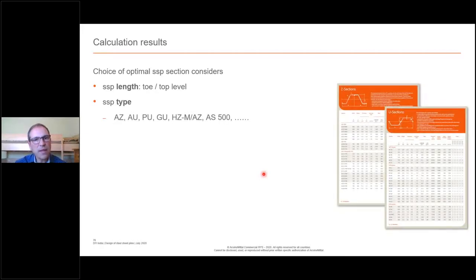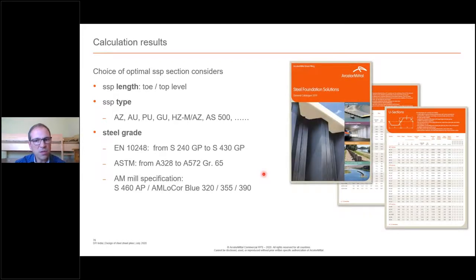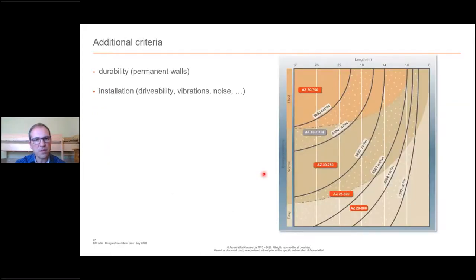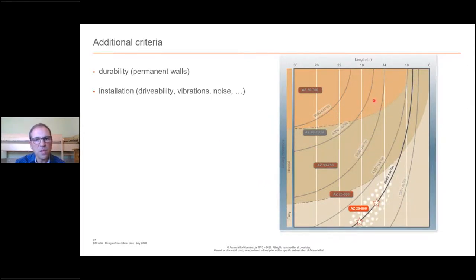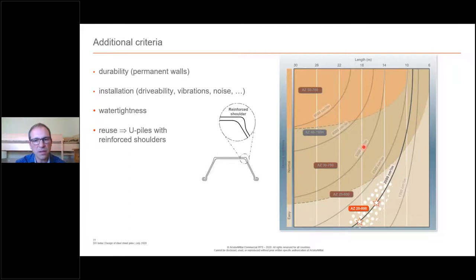So if I summarize, there are a few parameters: the sheet pile length, the sheet pile type, as we have seen, and then the steel grade. This is what you have to choose in order to verify the steel stresses. You also have to take into account durability, as you'll see, and installation. This is a chart that you can find in the piling handbook, where you see, for the soil conditions, easy, normal, or hard driving, the length of the pile that's recommended compared to the elastic section modulus. So it gives you an indication. It's not rocket science, but it's based on experience.